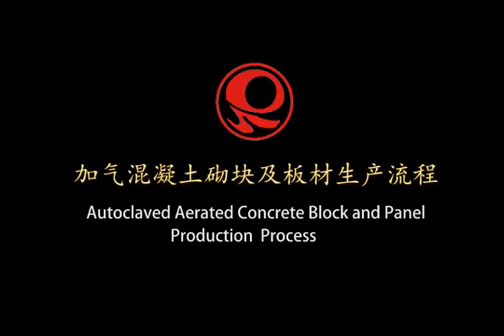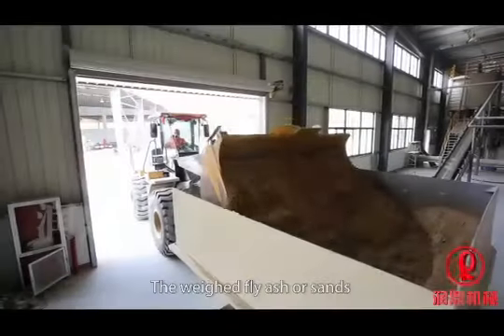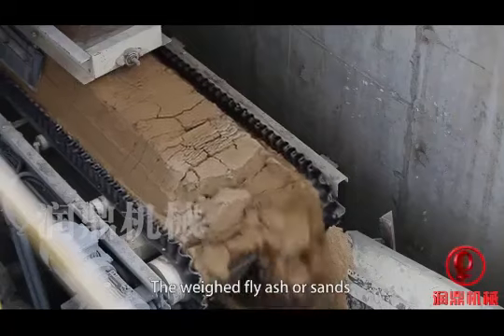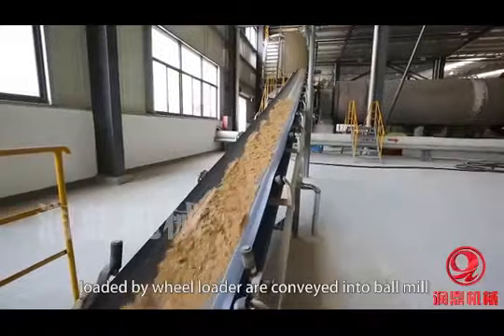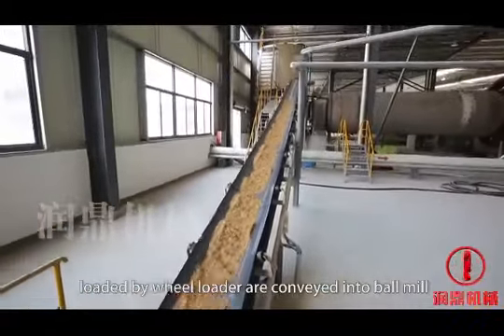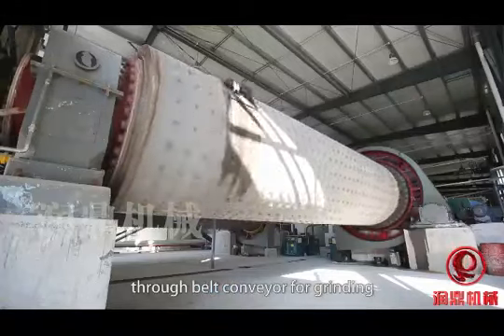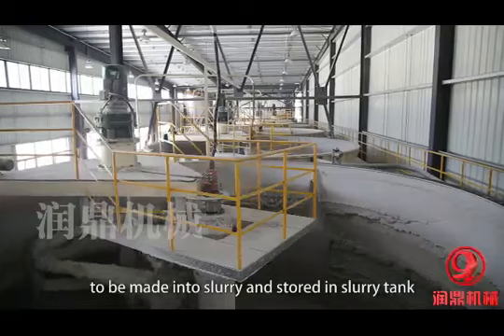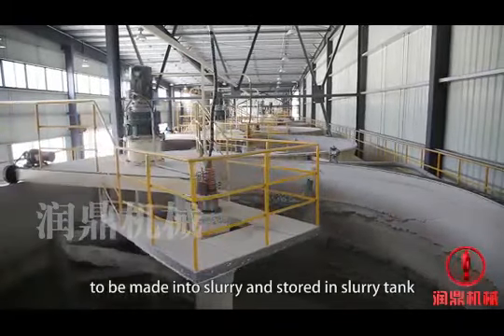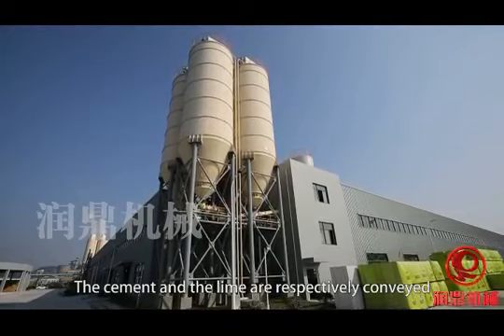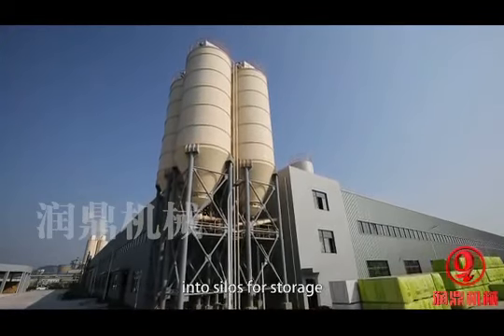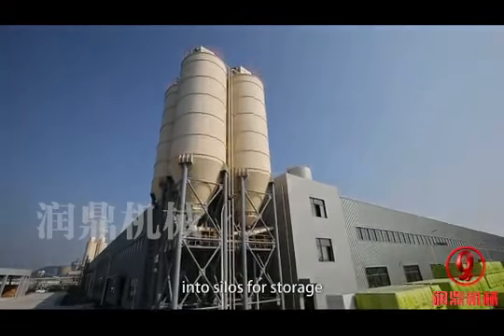Autoclaved aerated concrete block and panel production process. The weighed fly ash or sands, loaded by wheel loader, are conveyed into the ball mill through a belt conveyor for grinding, to be made into slurry and stored in the slurry tank. The cement and the lime are respectively conveyed into silos for storage.